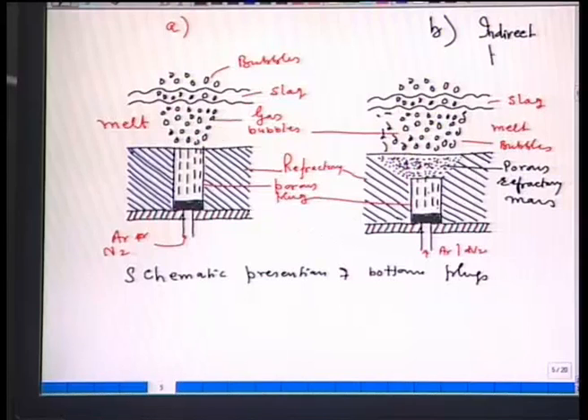indirect plug. The difference between the two, which is a very important difference: in A type of design, the plug is directly in contact with the melt. So, you can imagine the operational difficulties that could be there. A continuous amount of gas has to be injected through the plug, otherwise the melt will penetrate and some of the holes of the plug will be blocked, and then it has to go for repair.